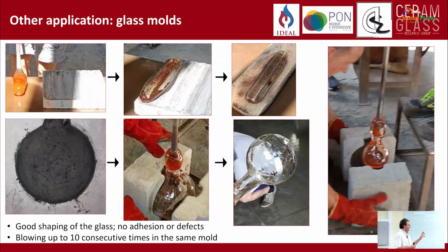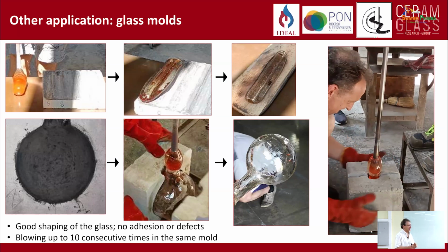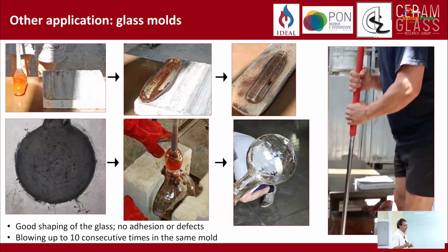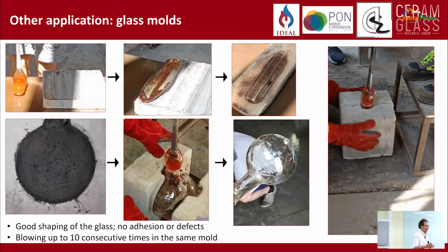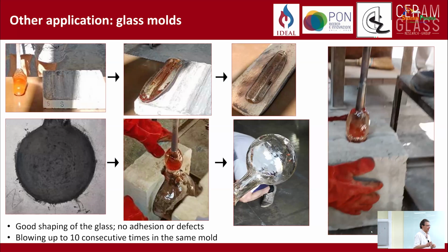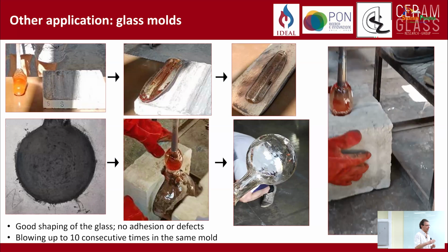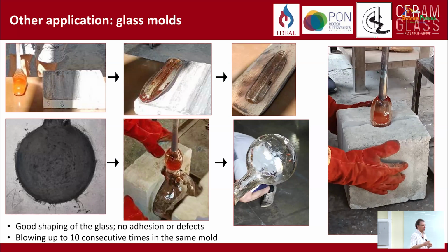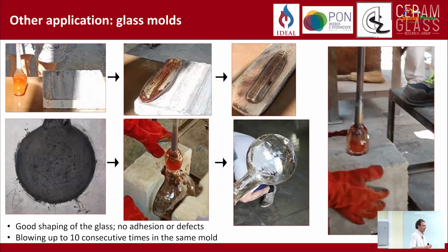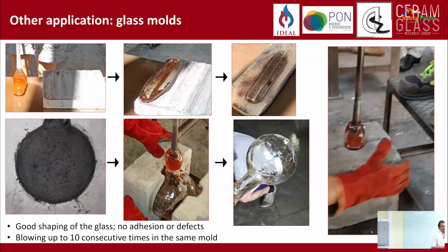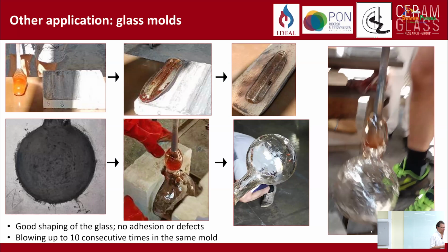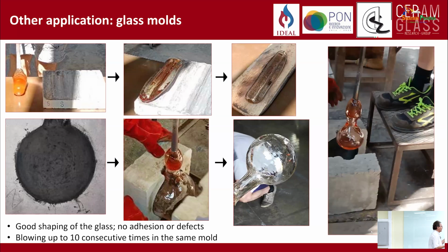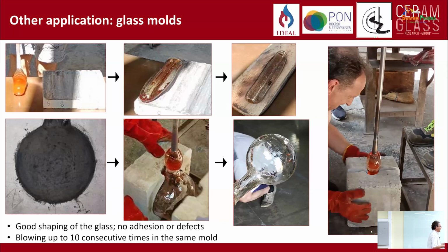And I didn't mention this for metallic molds. You typically use them up to, I don't know, tens of thousands of times. For a wooden mold, you typically use it between 100 and 200 times. And we reused the same mold up to 150 times without any issues in terms of cracking or degeneration of the surface. Of course, like in any molds, we need to reapply the coating after a few times.